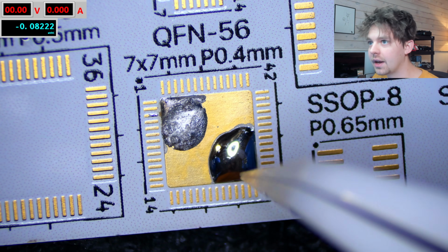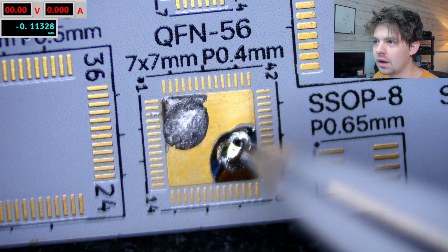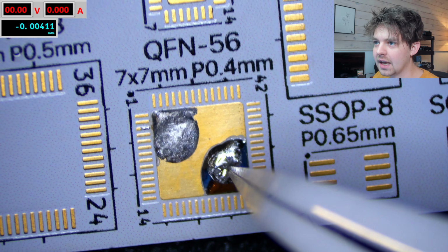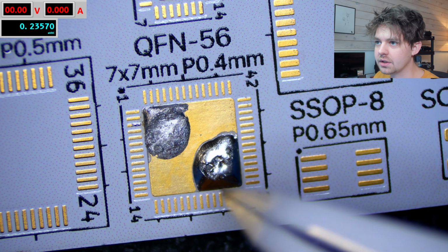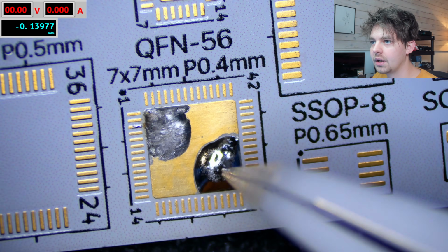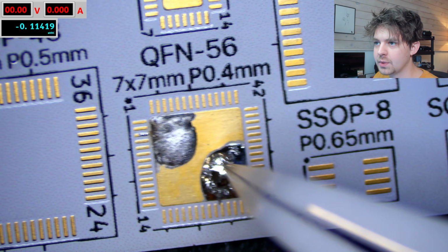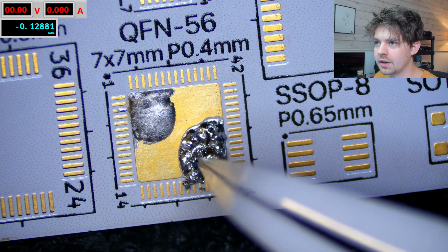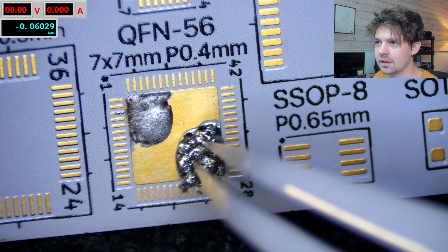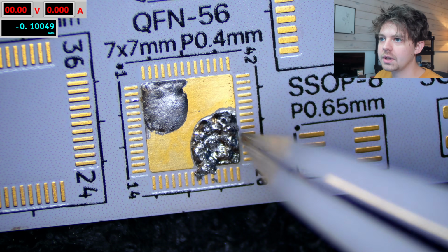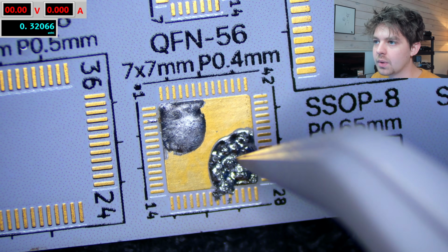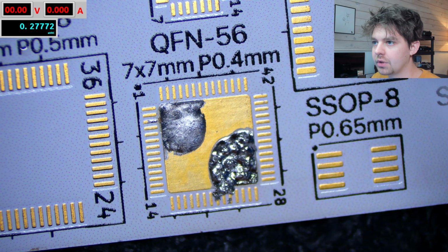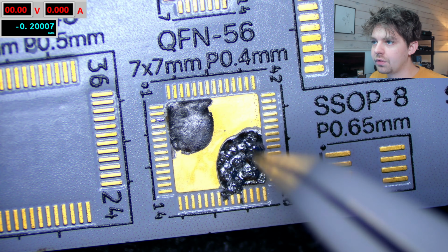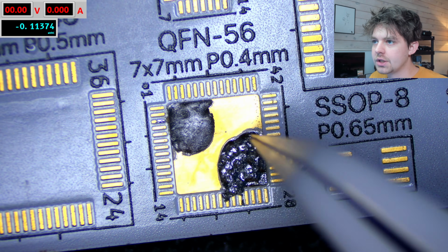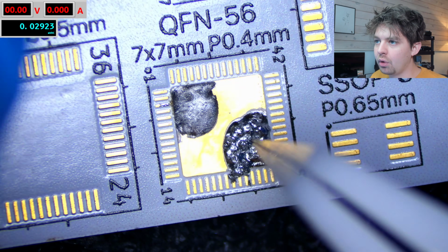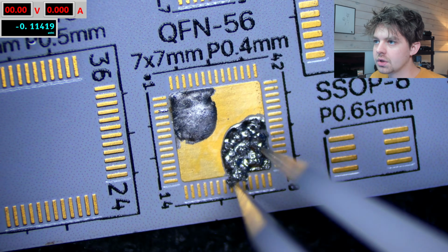So I'm going to melt this one again, and we'll move this one around while it solidifies. And I actually can't even move that around anymore because it just solidified. So we could try that again actually. I'm going to start moving it around, and my tweezers are probably just going to end up getting stuck in here eventually. Okay, no. So you can see the difference between these two. Neither of these look very pretty, and this is what happens when you move components around without flux while they solidify. However, you can hopefully see that the eutectic alloy here is shiny throughout still, even though we've moved it around quite a bit and made a gross looking heap.